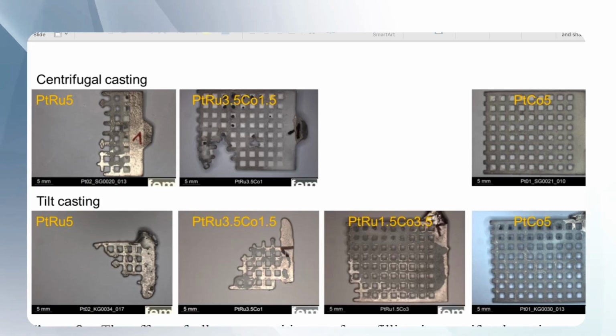These two alloys are the benchmark. And then in that paper where these figures are coming from, we were trying to improve the castability of platinum ruthenium by adding a small amount of cobalt. We saw that this is very effective, especially in centrifugal casting. If we replace 1.5% of ruthenium with cobalt, we nearly get perfect form filling. So it does not take much - this is, I think, a very interesting result.